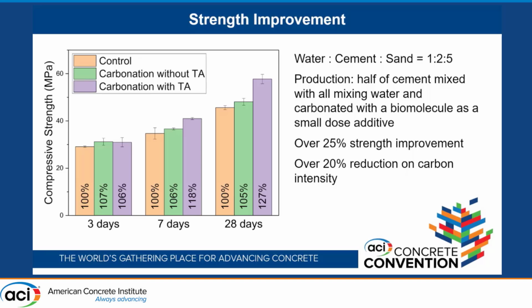And then, of course, talking about performance, we also want to look into strength. Again, here I have three samples. Basically, we have a control for reference, and then we have the carbonation without the tannic acid versus with tannic acid. You can see that even though you are able to get some improvement, which would be similar to what you see with curing and mixing carbonation, because it would be a similar amount of CO2 in the mix, once you add the tannic acid, you're able to bump that performance to over 25% improvement by 28 days.